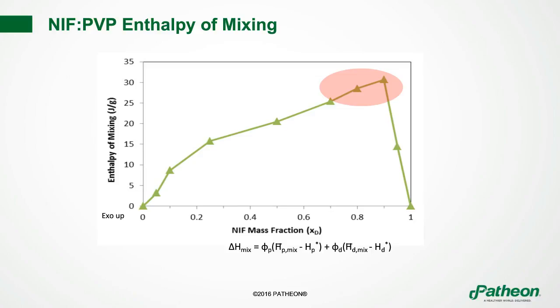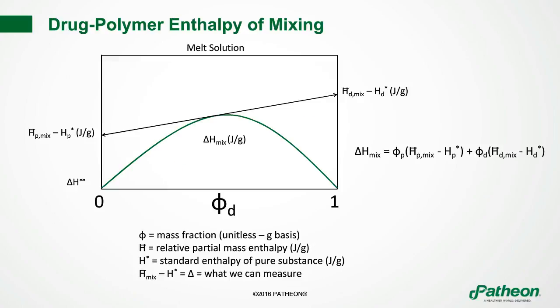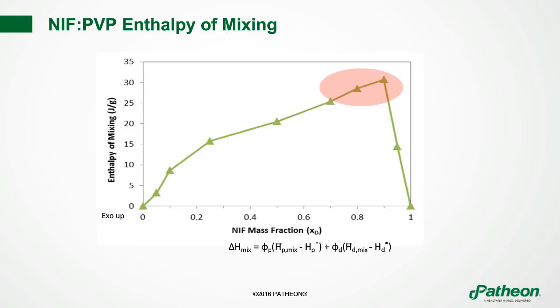And what we see is a similar type of shape as in the previous slide, which I'll go back to real quick. You see this parabolic shape. Well, in this slide, you also see somewhat of a parabolic shape. And we believe that these points out here, where we've got the red ellipse, are areas where the amount of drug added to the polymer is very high and the amount of polymer added is low. So we might have some inconsistencies in our measurement in terms of the weight fraction, the mass fraction of drug and polymer, and so we think these might be slightly in error.